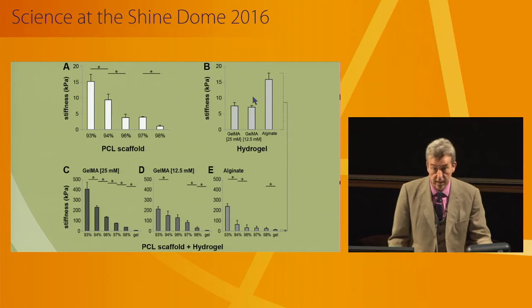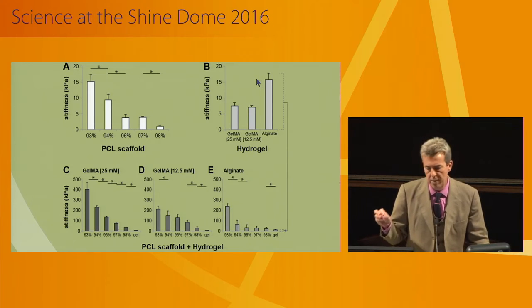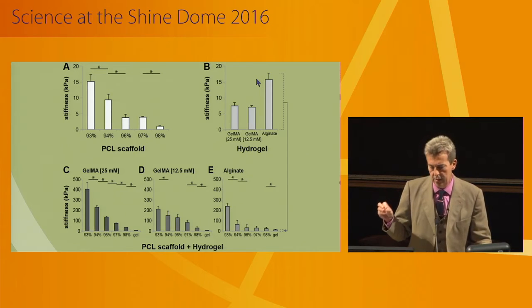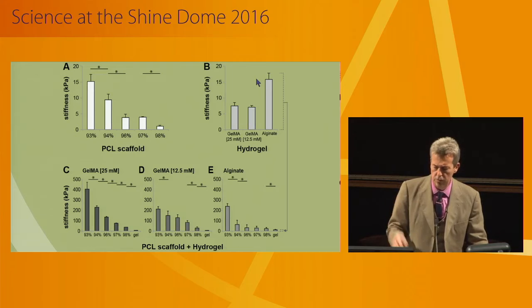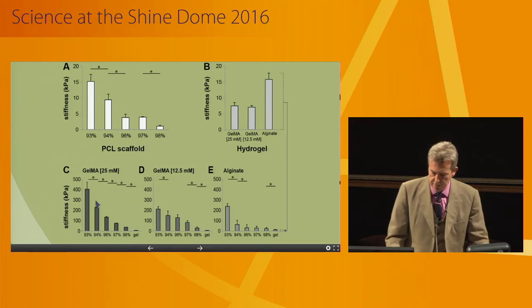If we do a cross-linking, which allows us to have, again, cell proliferation and ECM formation, then we are in the same range of 10 to 15 kilopascal. But the great thing is now, if you combine the system, and this melt electrospinning allows us to go down to fiber dimensions also of 1 micron, then you see here that you get an up to 50-time increase of the mechanical properties of the system if you combine the fibers with the hydrogels.